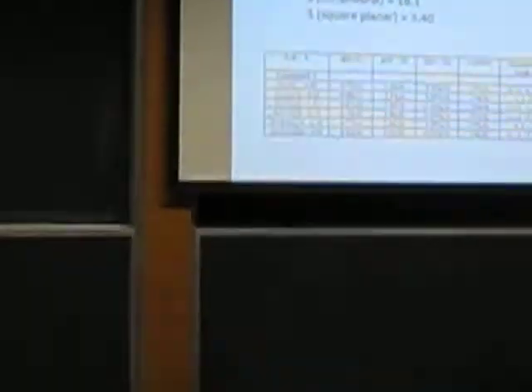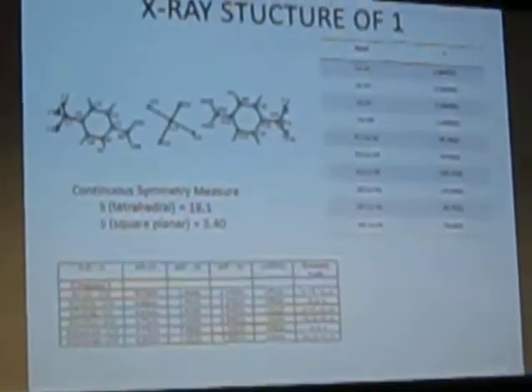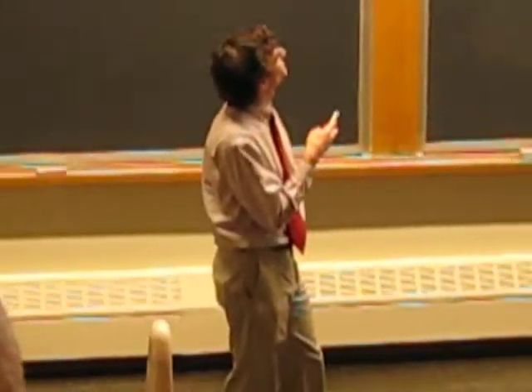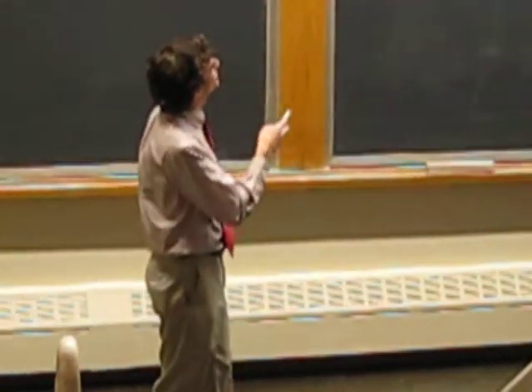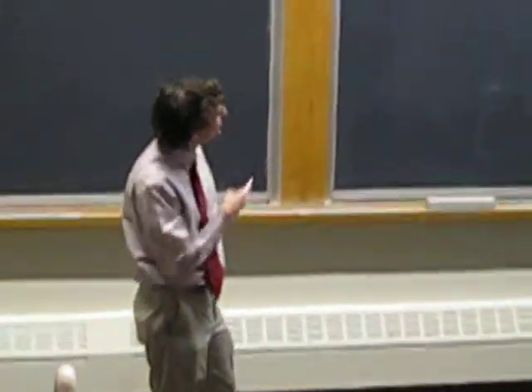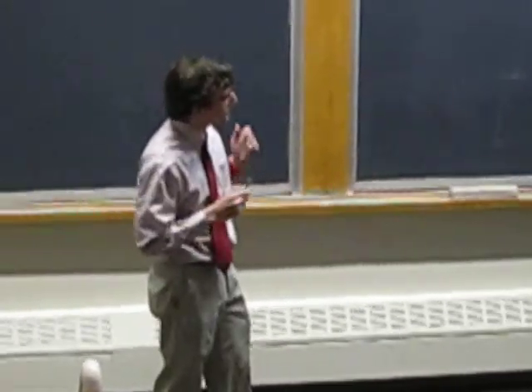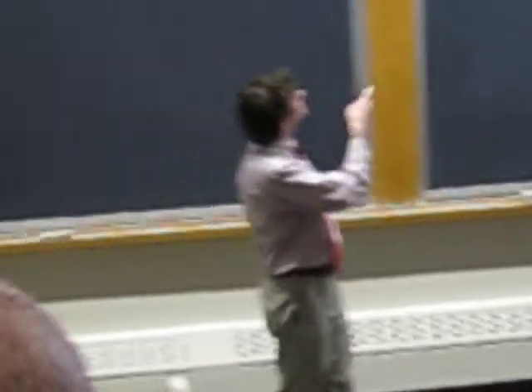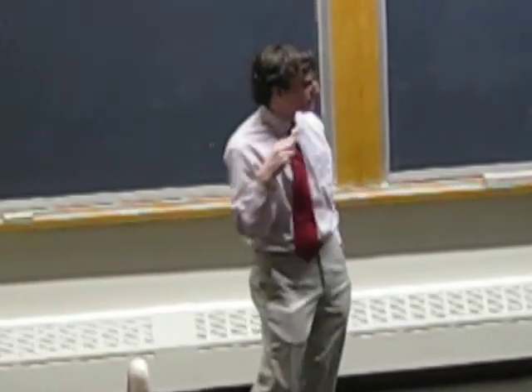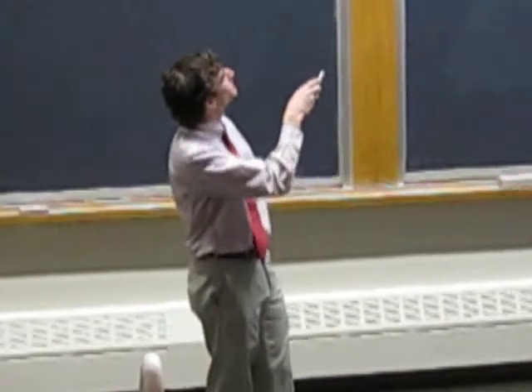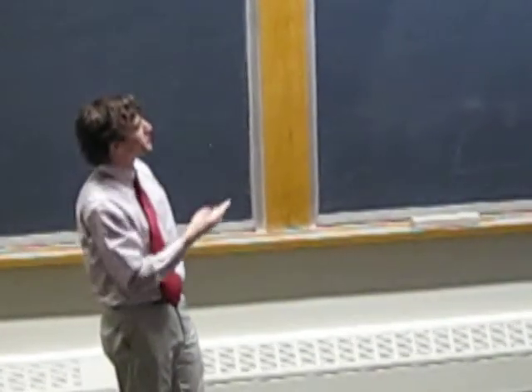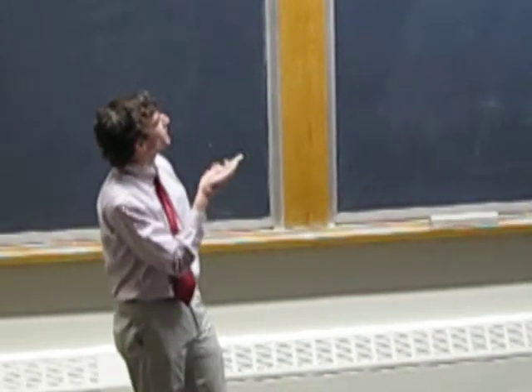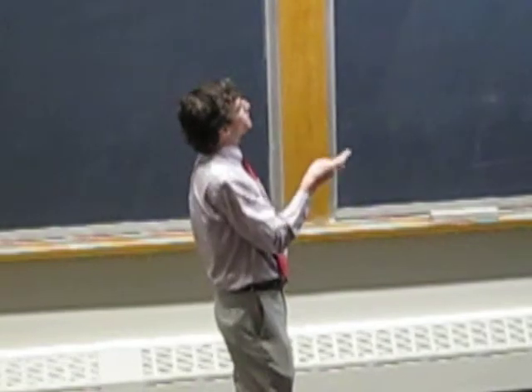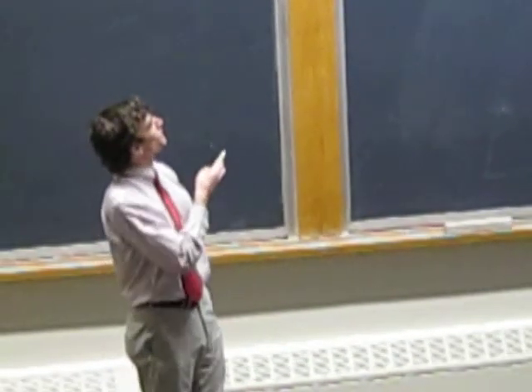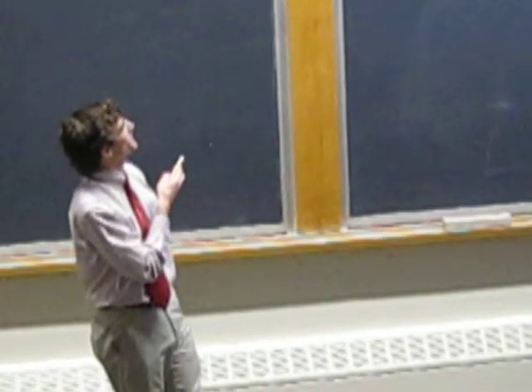This is the asymmetric molecular unit. So here are the two rings on either side of the tetrachlorocuprate. Just looking at the geometry around the metal center here, we took a continuous symmetry measure, which is essentially you take the difference between an idealized structure, let's say the tetrahedral structure, and the atomic positions of the atoms here in the crystal structure, and the difference will give you an S value where S values closer to 0 are closer matched to that particular geometry. So you have to do the measurement for each individual ideal case.